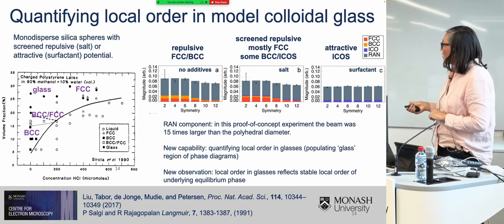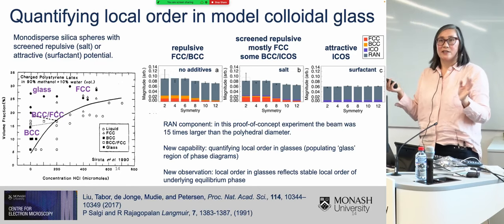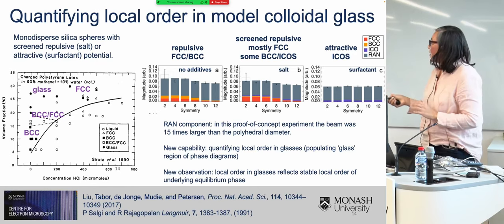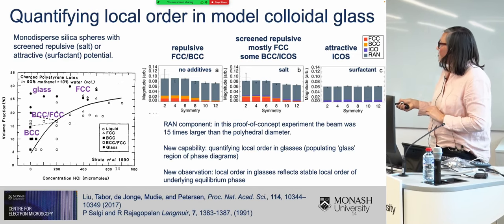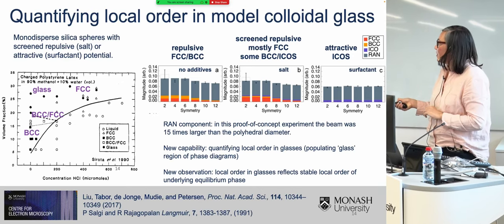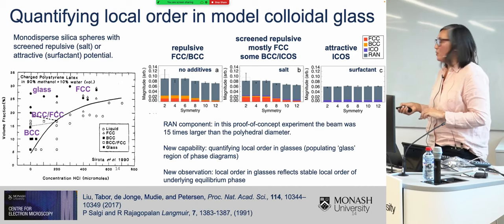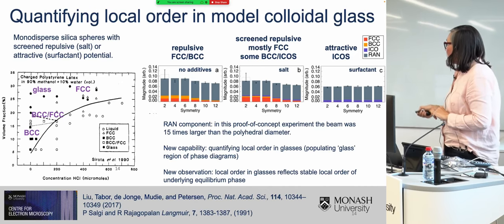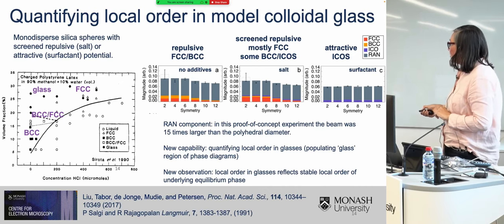So you can think of that as populating this area here of the phase diagram, where people just said, that's a glass, that's a glass, that's a glass. Now we can say, this is a glass that has FCC dominant order, this is a glass that has BCC dominant order. And then we've also made a new observation, which is that somehow the local order in glasses reflects the stable local order in this underlying phase diagram.